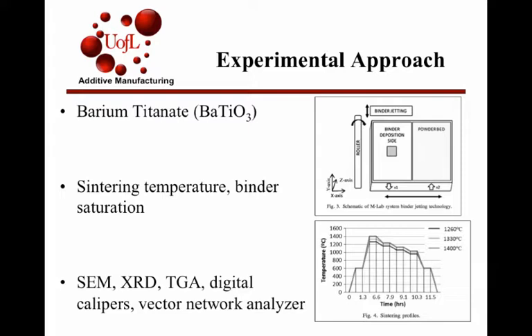The second diagram at the bottom there shows the sintering process, how they did it for each different material. They did 3 different temperatures, and this is how they sintered it over time. So the first hour and 20 minutes, it went up and stayed at 600 degrees, and then they took it all the way up to its max temperature at a steady rate. And then once they reached the max temperature for the setting, they would walk it down every hour or so, just to give it that entire sintering process.